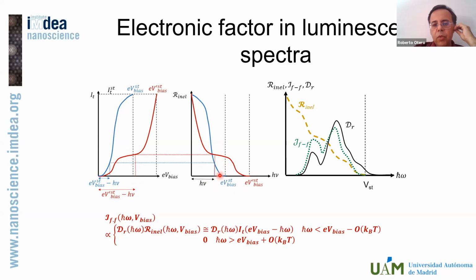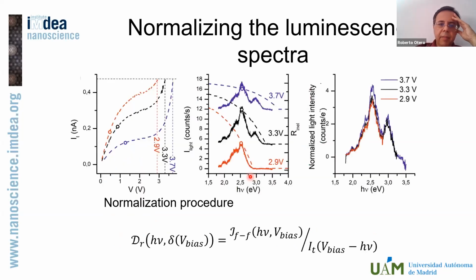And if I do the same thing at a different voltage, then same thing. So if I measure the IV curves of my tunneling junction, I can calculate the rate of inelastic tunneling as a function of the photon energy simply by reverting the curves and shifting the zero to the applied bias voltage, right? Let me show how it works.